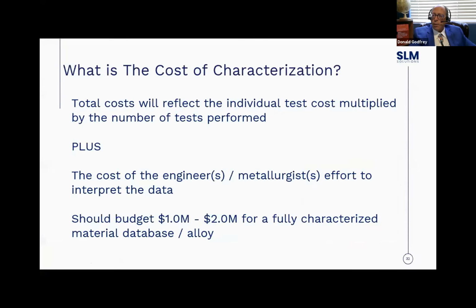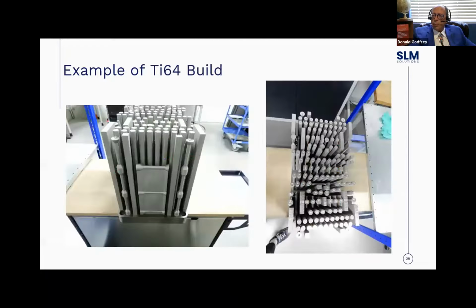Okay. So to validate the process, let's say I'm going to validate that I have the correct machine parameters. Let's take a look at this titanium build. And the reason you want to build it this way is, well, there are several reasons, right? So what you have here is 1, 2, 3 tensile specimens in height. If all your parts were short, you would only have to build tensile specimens the height of your part, right? But if you have a tall part, you want tensile specimens from the base plate to the very top